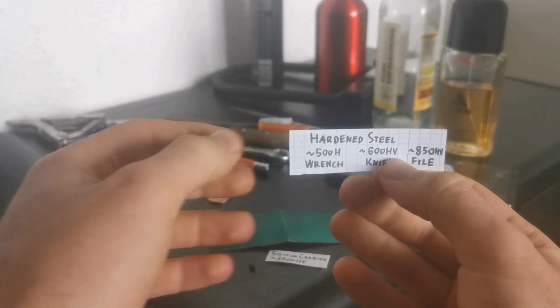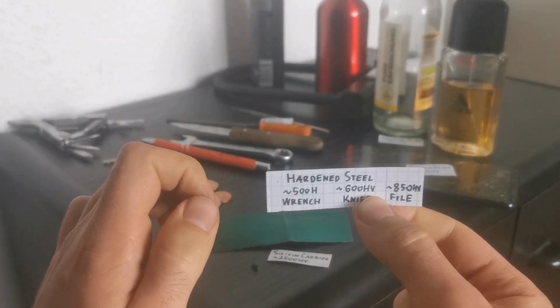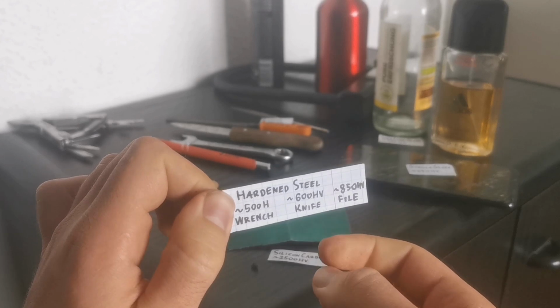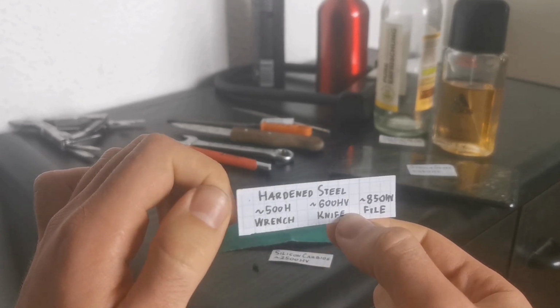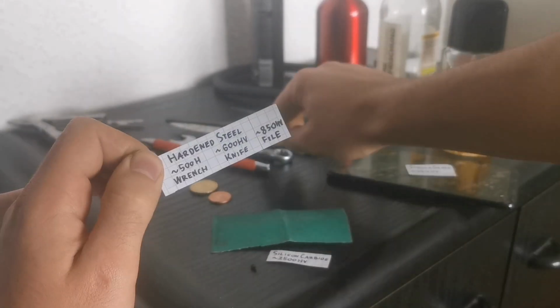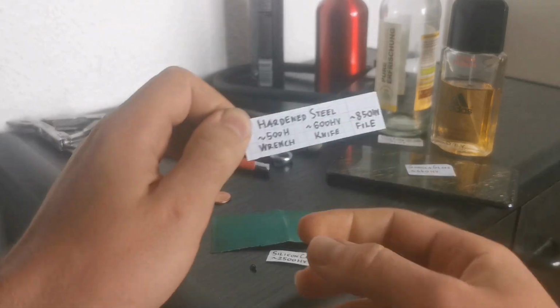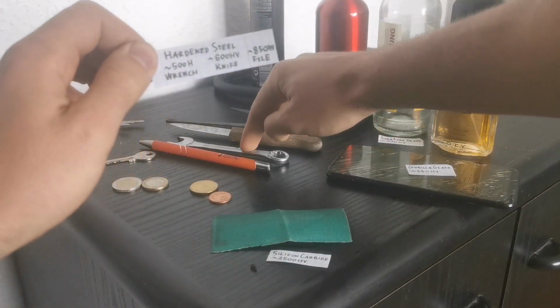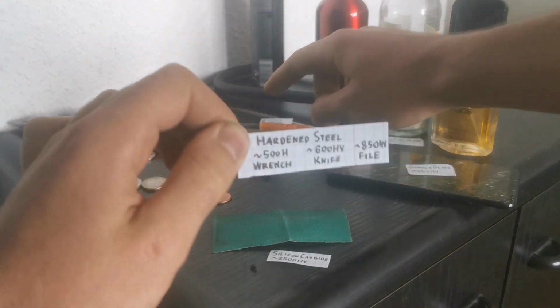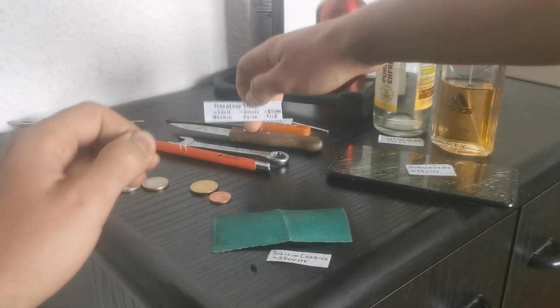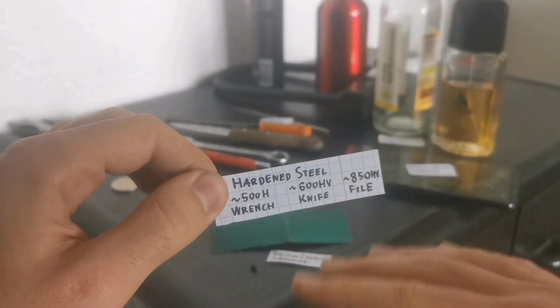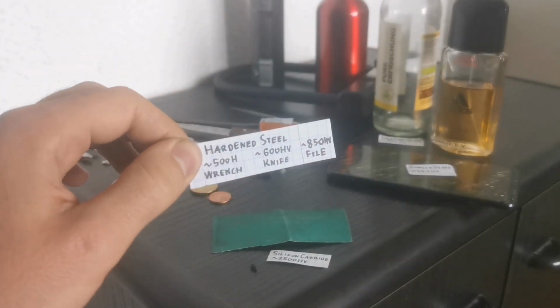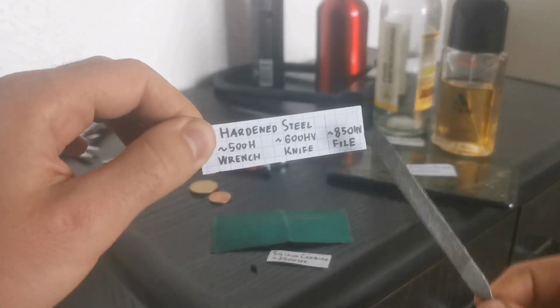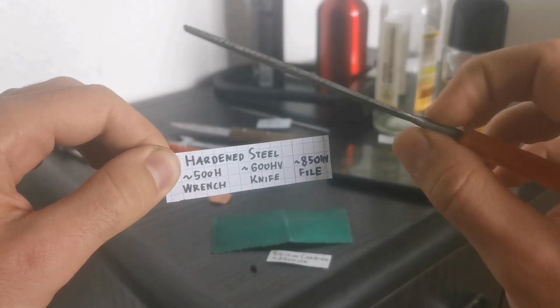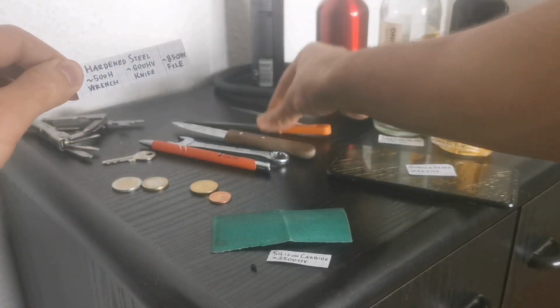And steel after hardening can have various amounts of hardness, and I measured for those items that the range is around 500. This translates to around 50 HRC. The knife is around 600, which is around 55 HRC, and the steel file 850, which is around 64 HRC.